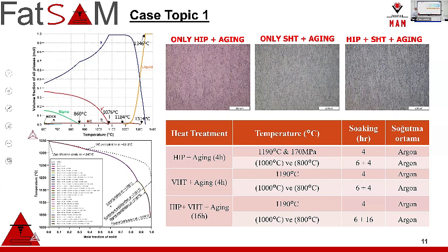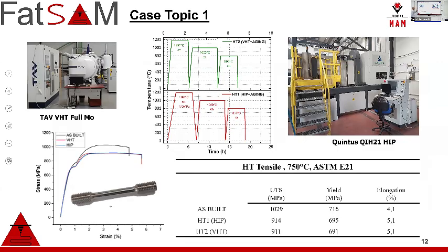So we tried 3 experiments. Initially, we performed the first 2 and 2 tensile tests before passing to the creep and fatigue test. We observed that it doesn't work. So we have to focus more. The basic HIP and solution approach as we used in cast materials doesn't work. So as you can see, the elongation is very low. Strength in as-built condition is even higher than heat treat 1 and 2.